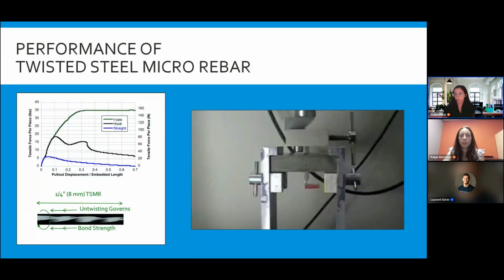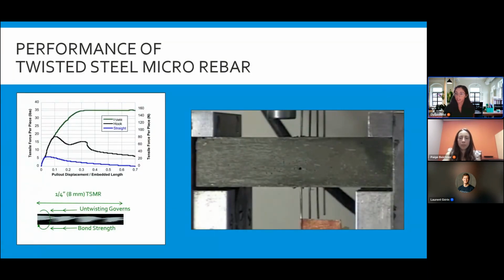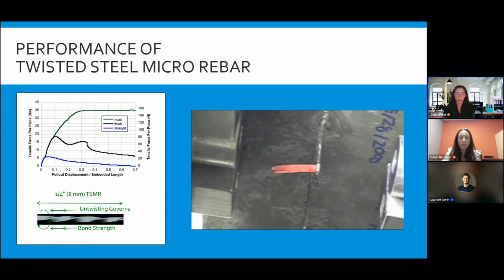And so if you look at this video on the right, you can see that we have anchors attached to a fiber. And if you watch that flag, you can watch it untwist in real time as load is applied. And this graph on the left shows the different behavior between a twisted steel micro rebar fiber and then a hooked fiber and a straight fiber. So you do need significantly more force to pull a twisted fiber out of a concrete specimen than you do a hooked or a straight fiber.